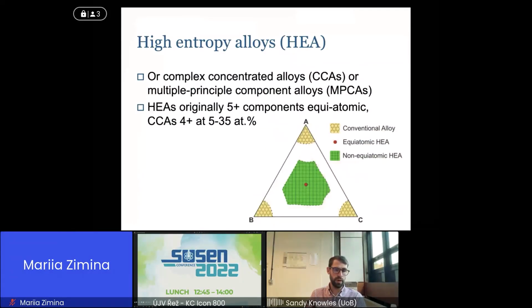So the initial observation was Brian Cantor and Ye, who separately came across this concept, mixing together, if I remember off the top of my head, cobalt, nickel, manganese, iron, chromium. These are elements that are on the common row on the periodic table. But if you mix them together with the differences in crystal structure, you might anticipate that you would either get many crystal structures or you even would form intermetallic phases. But the unusual observation was that they got a single phase FCC material. And it had properties that were very different to any conventional alloy. And so this idea has caught a lot of interest in how we could discover and demonstrate new materials.